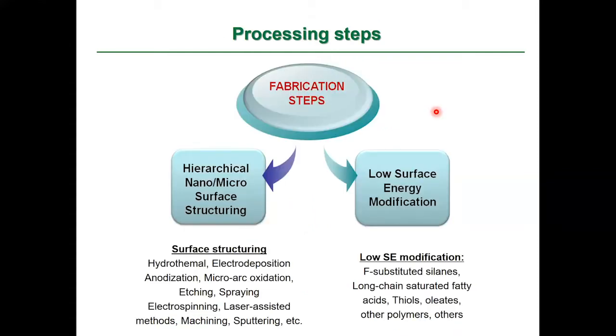So in general, we can classify the fabrication steps into two. As we already said, hierarchical nano-micro surface structuring and low surface energy modification. In the hierarchical nano-micro surface structuring, we can use hydrothermal method, electrodeposition, anodization, spraying, machining, sputtering. A lot of methods are employed for that. Low surface energy modification also can be applied by some of these methods, or simple immersion can be applied for making a surface with low surface energy. Typically we use fluorine substituted silanes or long chain saturated fatty acids as low surface energy materials.